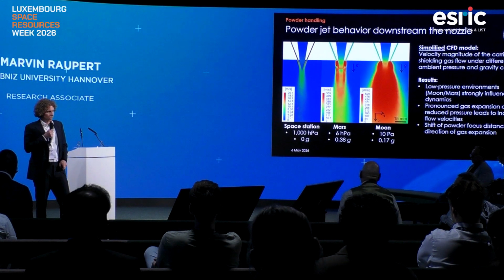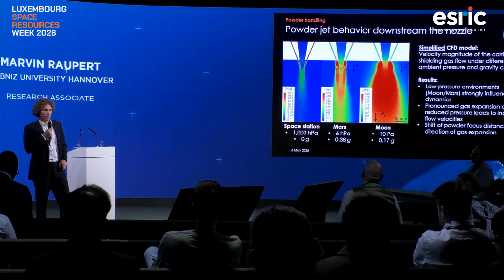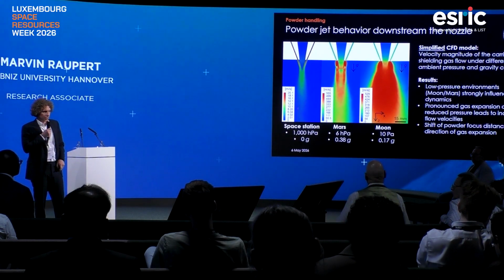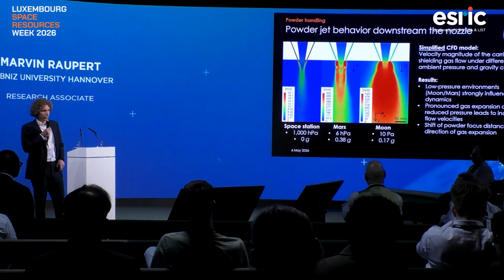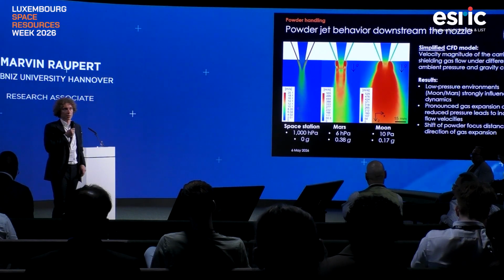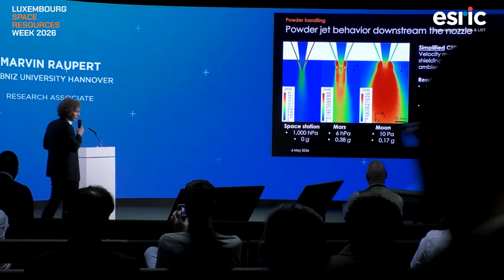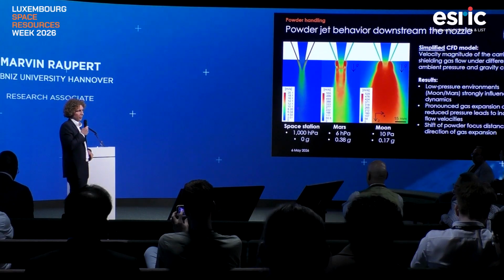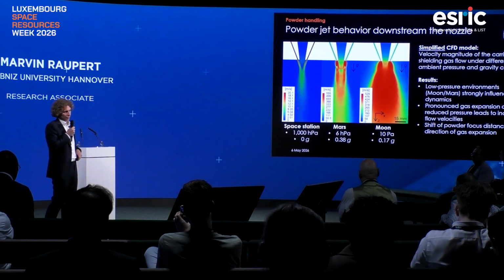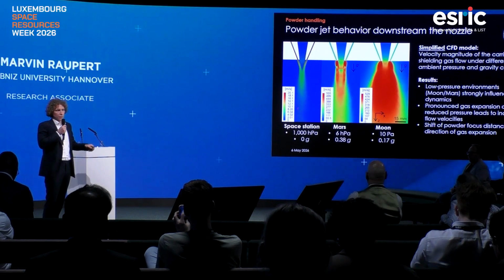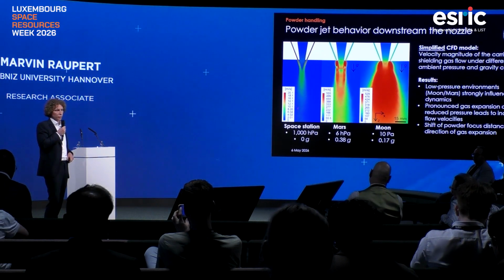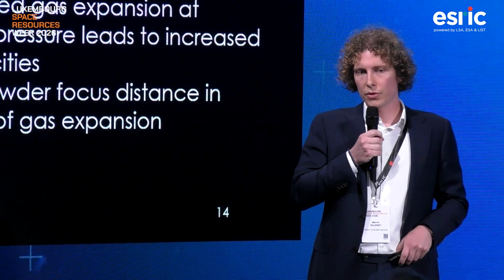Just don't worry, the 10 Pascal is there because that was the minimum limit in our simulation. And what you can see here is also that the velocity level of the gas flow, of the carrier gas and shielding gas, will be over 500 meters per second when we are manufacturing outside of the laboratory, on the surface of the Moon and Mars. In fact, with the common process of LPDED, it would not be possible to manufacture the specimens because the high velocities would just blow away your melt pool.